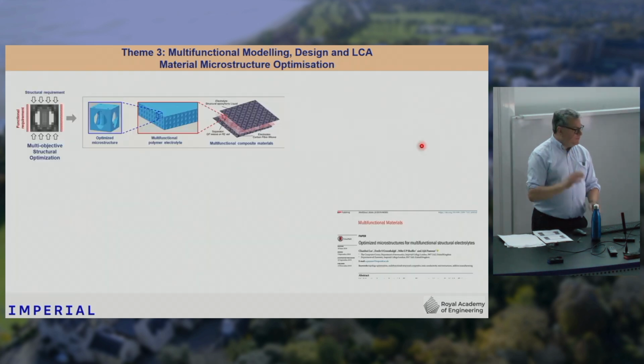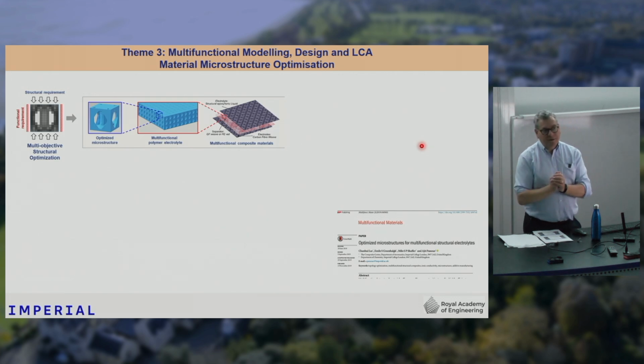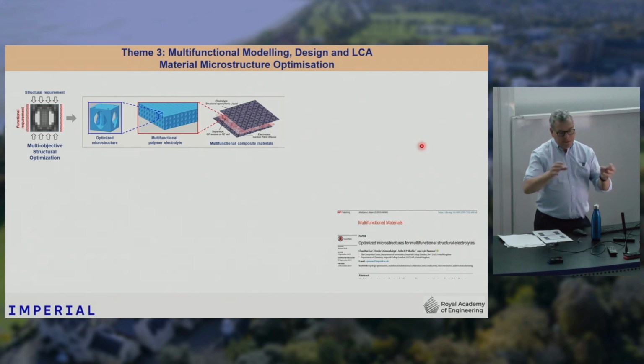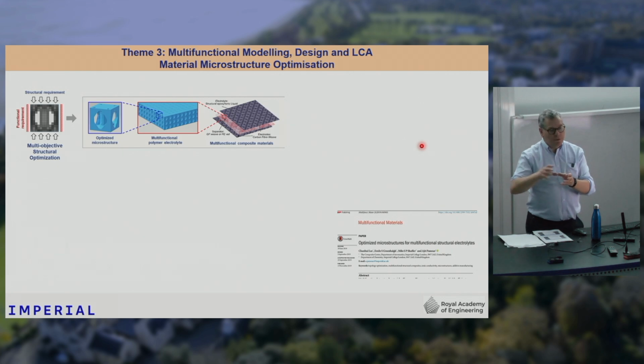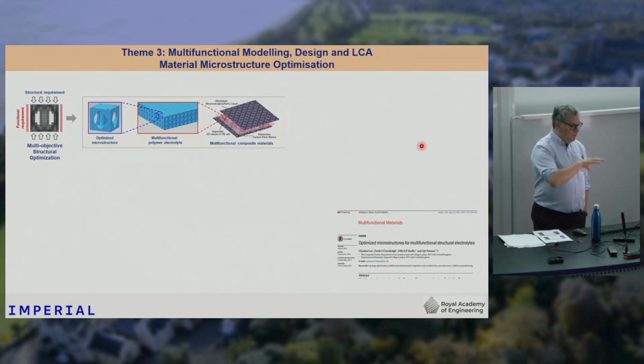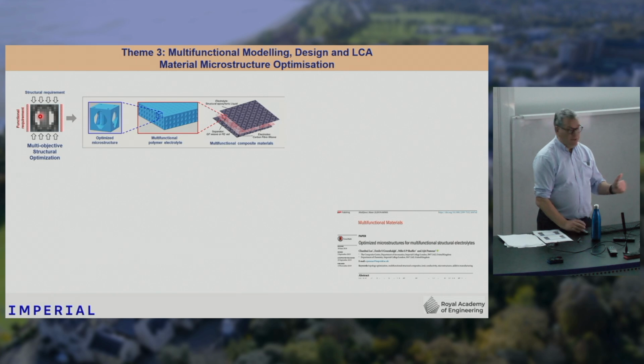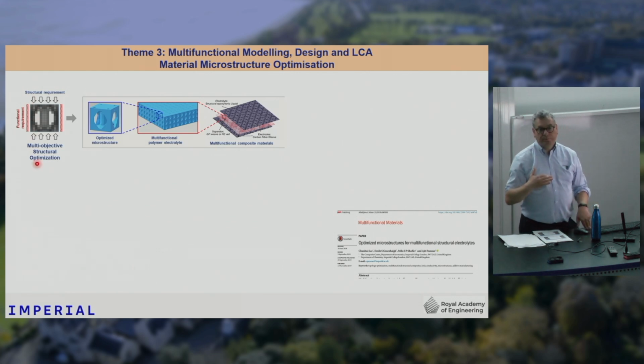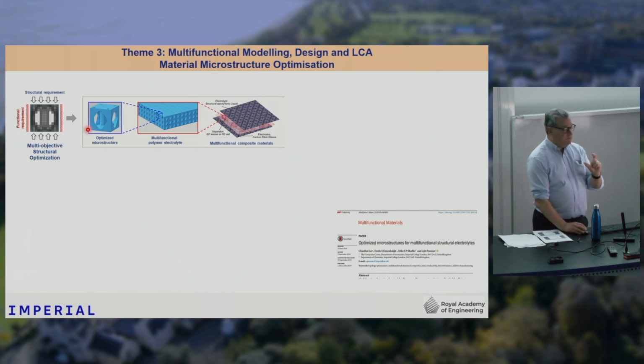So one of the first things we started embarking on is, having worked with the chemists, everything they're doing is very much experimental. They mix the constituents together, they produce a microstructure, they change the performance, it changes the microstructure. But we never really knew what's the perfect microstructure that we want for our device. So we thought modeling would be the approach to achieve this. We want to produce a representative volume element of our material, and that volume element has to have a functional requirement. It has to allow ions to move, say, horizontally through the material. But at the same time, it's got to do a structural requirement. It's got to carry mechanical load. And so the idea here is that you would have this optimized representative volume element that you would essentially build your electrolyte out of to produce your structural power material.